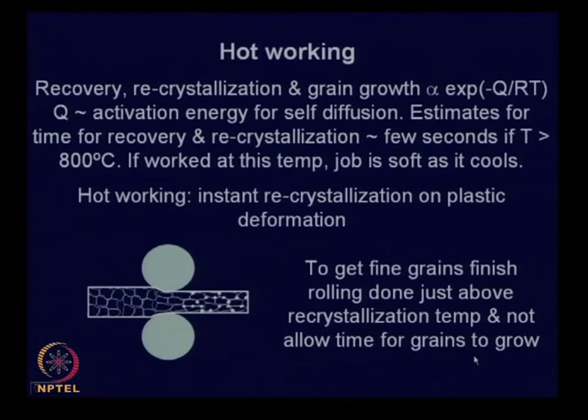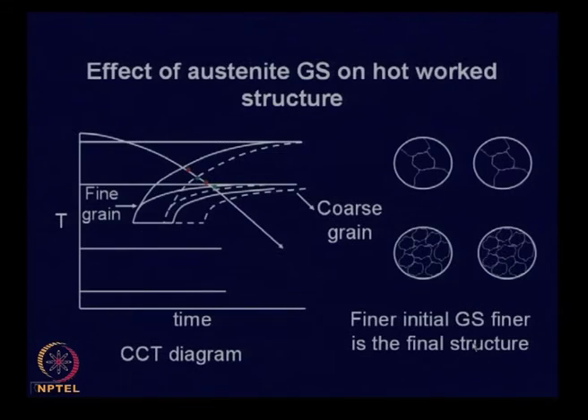So, the key to develop a fine grain structure, if you are doing it by hot working, is that you give all that reduction, the major reduction, bulk of it maybe at a high temperature where you need low rolling load, but the finished rolling temperature should be low, and at this finished rolling temperature the reduction should be a little high. So that your critical nucleus size is less, and the finished rolling temperature is close to its recrystallization temperature. So, as it comes out of the rolling mill, it does not get enough time for the recrystallized grains to grow. And also the austenite grain size determines that finer structure.